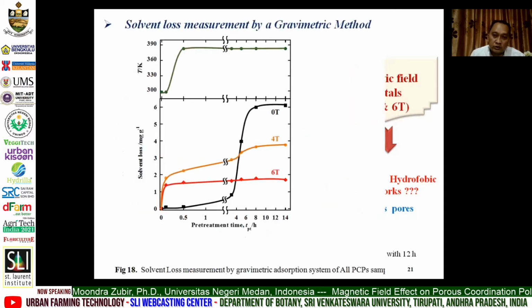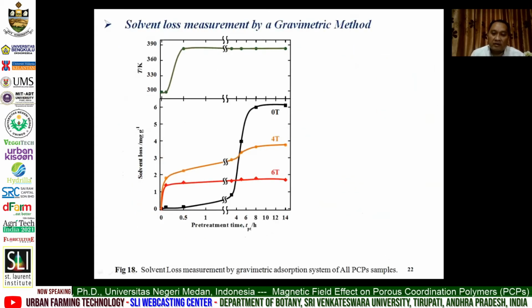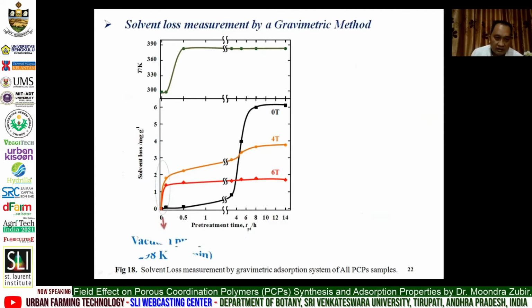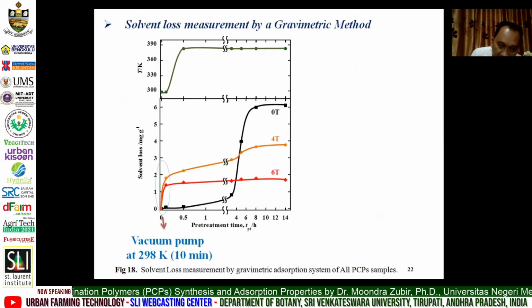So to prove this hypothesis, we do the solvent loss measurement by gravimetric method. In this initial stage, the first stage, it's only vacuum pump at 298 Kelvin for 10 minutes. So only by vacuum pump at 298 Kelvin for 10 minutes, all magnetic field crystals can remove the solvent if compared with 0 Tesla.